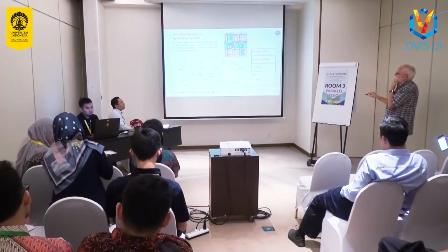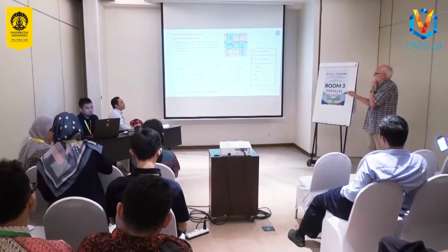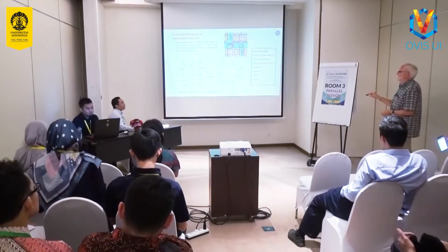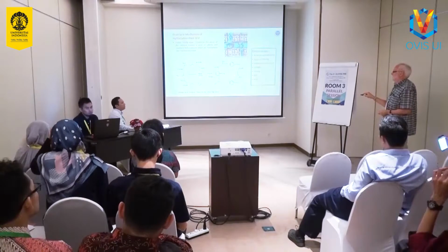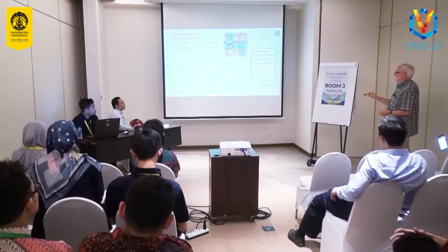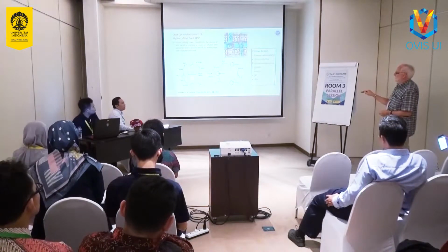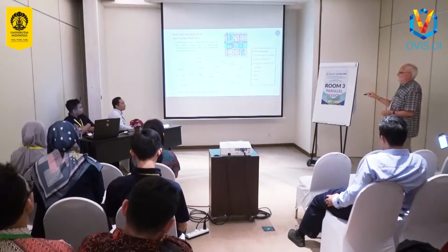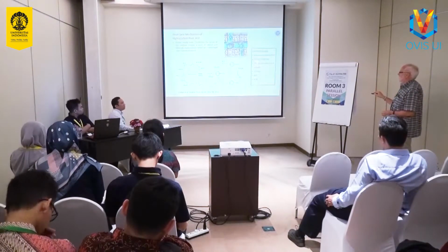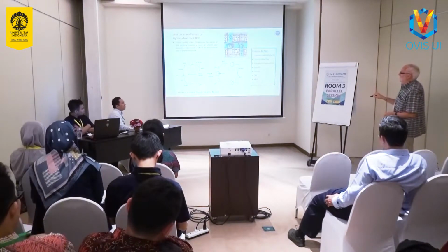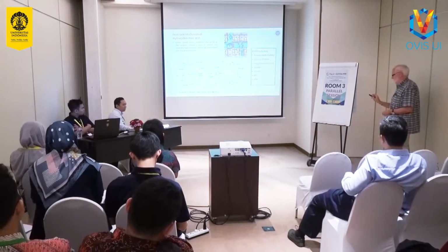Infrared doesn't work so well, actually, because as the catalyst ages, it gets darker and darker in color, and it gets impossible to measure infrared spectra from the catalyst at later stages. But people will use solid-state NMR, for example, to see some of these things. They'll also dissolve the zeolite and examine what's inside by GCMS, for instance. And the kinetics of the process are very consistent with this sort of autocatalytic dual cycle mechanism.